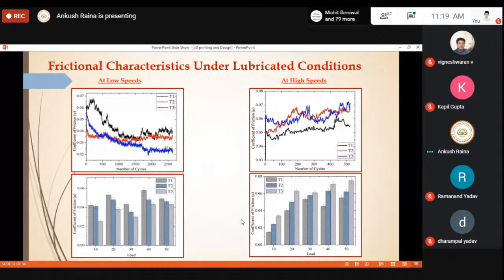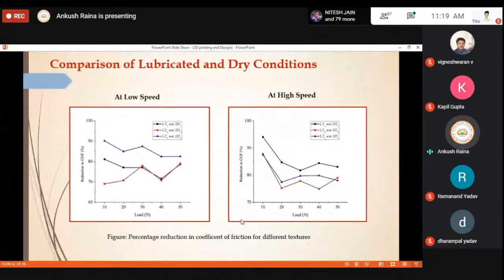optimize, or we can customize the parameters or the properties as per our requirements. So if you take into consideration the comparison at the high speeds and the low speeds for dry condition testing, and for the high speed and low speed, dry versus wet, LT1 means lubricated texture T1 with respect to dry texture T1. So here in all the cases you will see that the lubricated texture has improved the coefficient of friction nearly by 80 to 90%. Lubricated texture T3 with respect to dry texture T3, this one is the curve. So this has improved the coefficient of friction nearly by 80 to 90%. So which certainly means that the lubrication and the oil retention capability of the texture T3 has resulted in your reduced coefficient of friction. Similar kind of results are also obtained at the higher speeds.